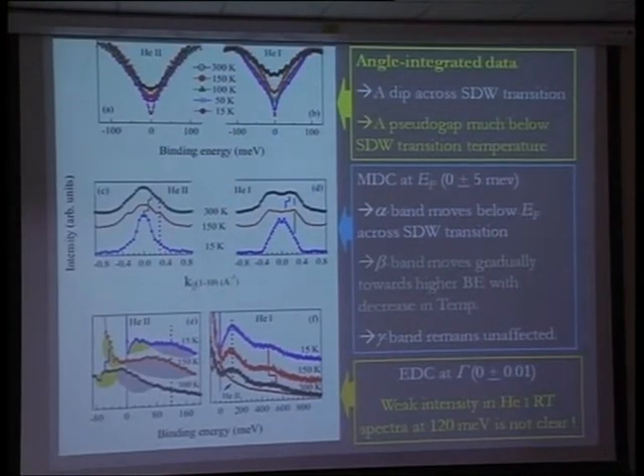And the second band, which is not so significant and not seen so much here, but which is clear in helium 1, also moves with reduction in temperature. Here you can see that this second beta band has come very close to the Fermi level. So we have done some intensity analysis here.